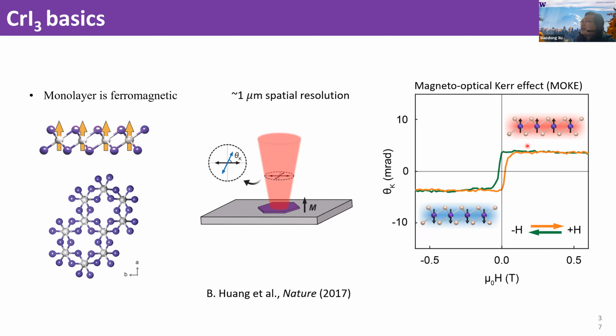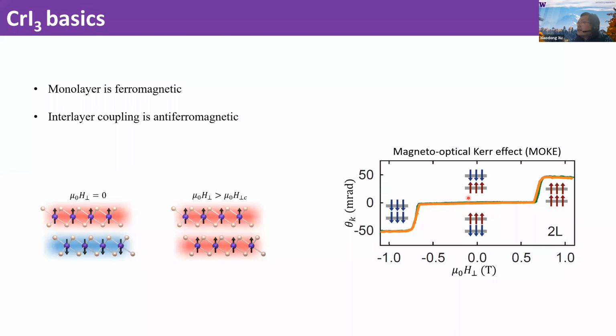The other interesting feature we observe is that in the bilayer, the Kerr signal actually vanishes near zero field. Then when the field is larger than the spin flip field, we see a strong Kerr signal appear again. So even though the monolayer is ferromagnetic, the interlayer coupling is antiferromagnetic. That's why in the bilayer we don't have any net magnetic moment at zero magnetic field. When the magnetic field is larger than the spin flip field, all the spins are aligned in the same direction again, a field-induced ferromagnet. That's why we see the Kerr rotation come back.